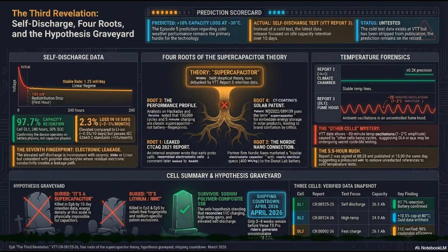Let's compare that stabilized 2 to 3% monthly leakage rate to the known technologies we have been debating since episode 1. Okay, first up, commercial liquid electrolyte lithium-ion batteries. Right. A high-quality commercial ion cell parked at a 50% state of charge typically experiences a self-discharge rate between 0.5 and 2% per month. So Donut Lab's cell is bleeding charge noticeably faster than a standard battery sitting in a Tesla Model 3 or an iPhone.